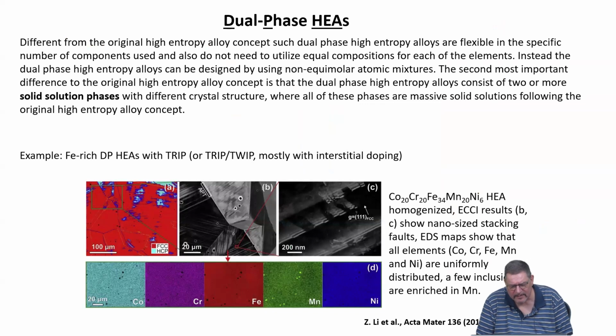When we now think of dual phase high entropy alloys, this is something which I think is more new, especially in iron containing systems, sometimes iron based systems. These studies have been like a continuation from steel-based research, because if you think about steels, some of them actually have rather large concentrations of additional elements in addition to iron, and all of them have a high number of functional constituents. So typically like 10, 12, 13 constituent elements, which each and every one of them has its own function to make higher strength or higher ductility, higher work hardening rate, and so on.